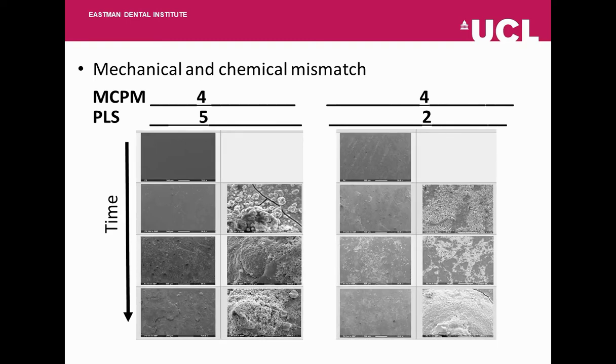And here is the same time period for the groups with lower levels of monocalcium phosphate at 4% and varying levels of polylysine. Again, we can see in both groups the formation of some sort of layer on the disc over time. So we can see in all the groups that over time, there is some sort of layer that's being formed due to the components within the disc, and of course, what's in the simulated body fluid. And this is mimicking a clinical setting of what may happen to this composite when it's inside the body.